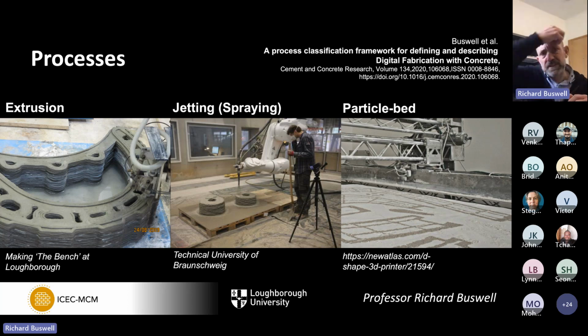The other method that's different is particle bed, and here what you do is lay down consecutive layers of, in this case, sand in thin layers, which in this case is about 10 millimeters, and then you inject some sort of binder to make it solid. So you end up with your object caked in loose material, which you can take out. Now, there's lots of variations of these. There's different binders used in particle bed. There's larger aggregates that have been used.